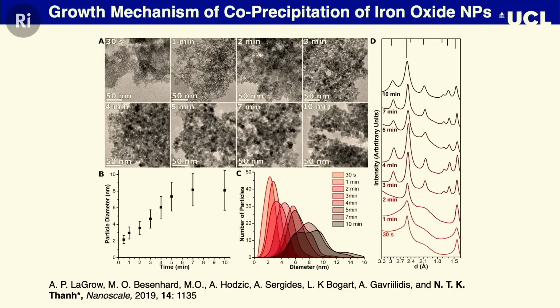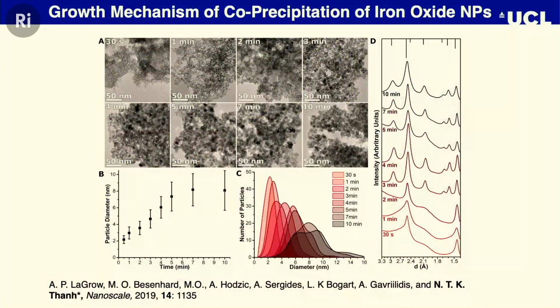So we looked into the reaction closely from 30 seconds to 10 minutes, and you can see the TEM along with the size of the nanoparticle and the size distribution. In the D panel, you see the electron diffraction pattern, and you can see the lines coming down. They are the positions of the magnetite peaks. And you can now start to see that from 2 minutes, magnetite is forming. Even here, at 30 seconds, you start seeing the signature of magnetite forming.